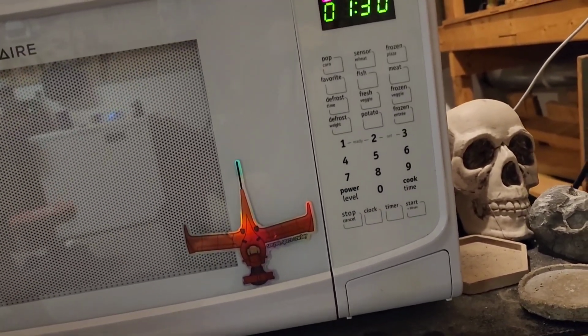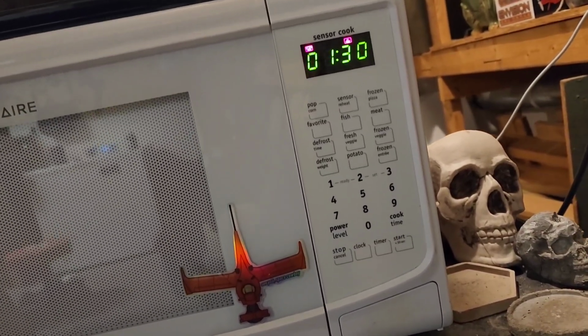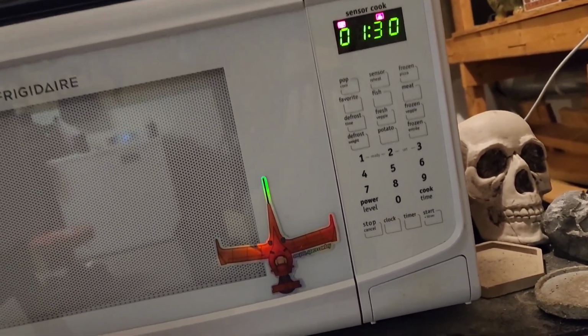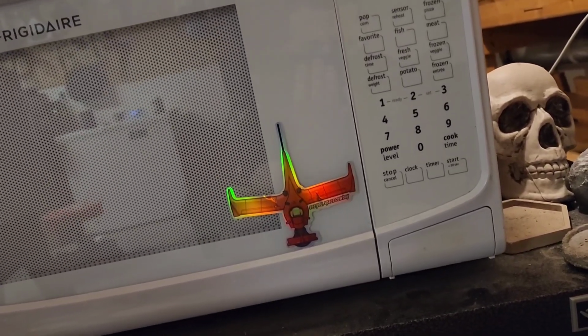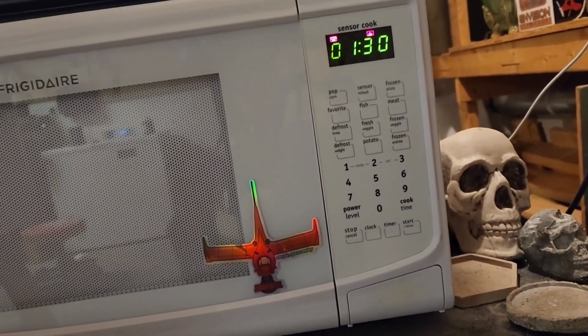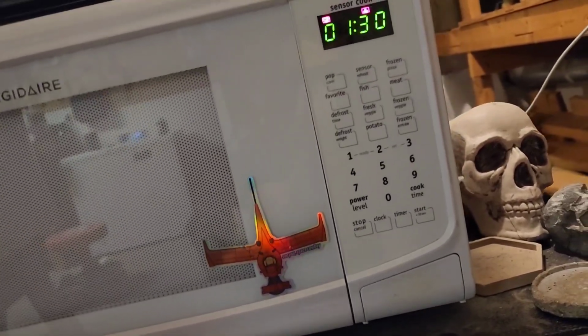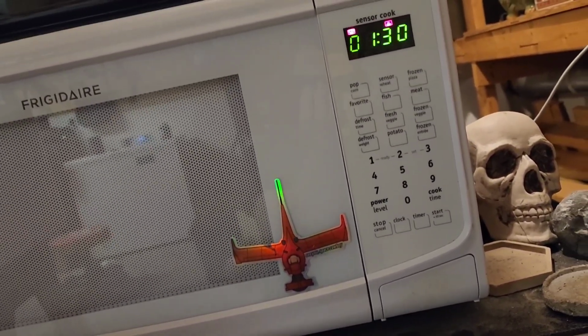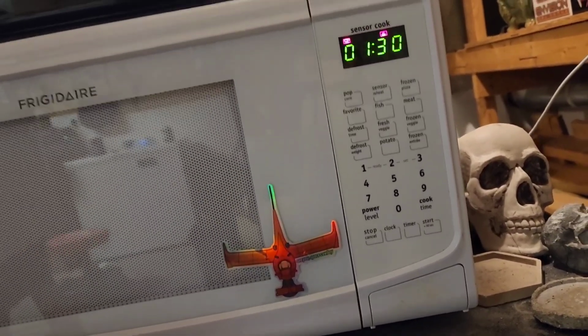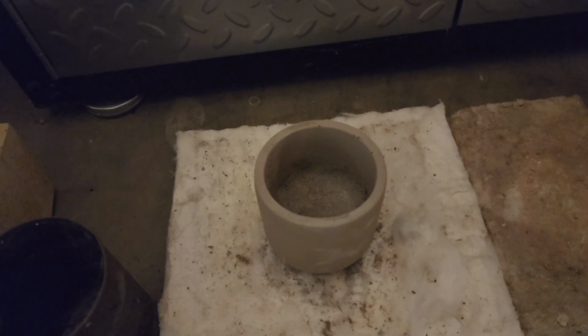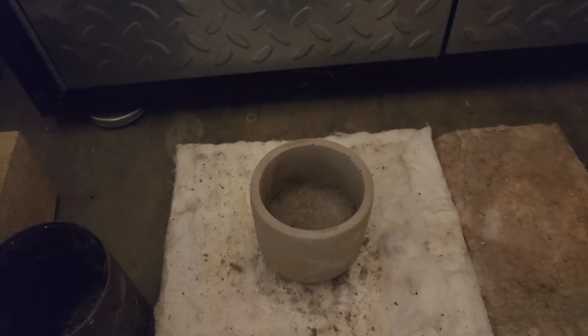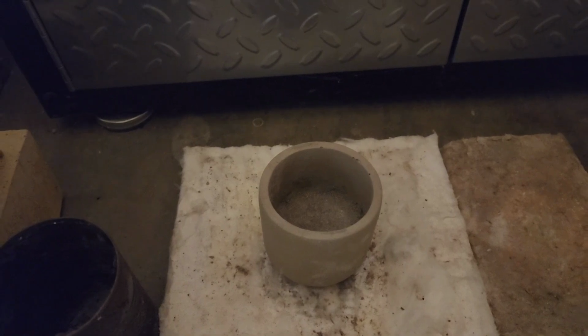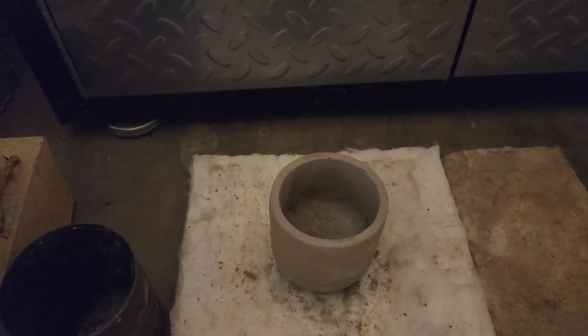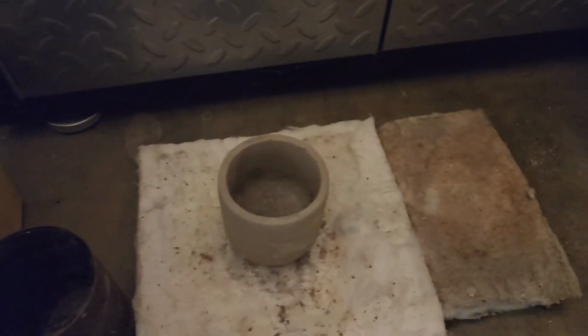The process that I'll be following is 1 minute 30, full arc sinter, 100% power level, and take out, then rotate and recharge the crucible with another load of media, and do this 4 times. So currently this is the crucible that is strictly microwave arc sinter. I will then move to the pre-sintered crucible and do the same exact routine. This one had the pre-sinter phase first, but following the same microwave arc sinter, and we will be measuring the results after that.